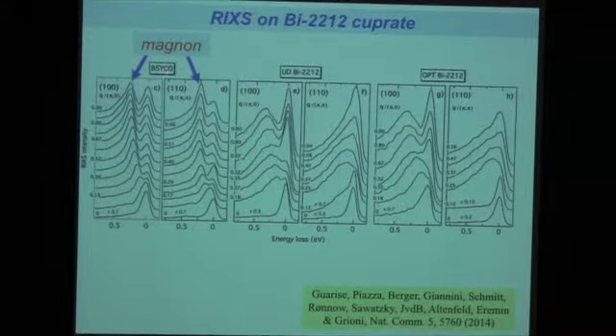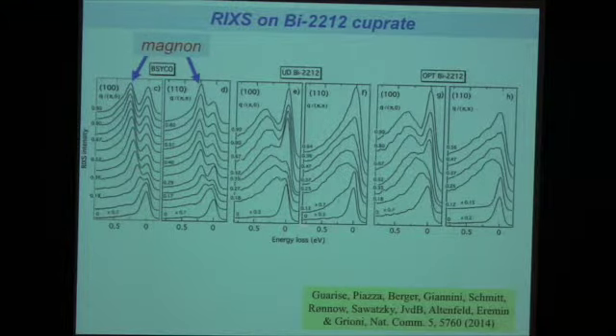Now, this is not doped, an undoped system. This is an under-doped system. This is optimally doped Bi-2212 superconductor. So these are now two directions. This is again momentum going to (π, 0), so from 0 to (π, 0), and here momentum going from 0 to (π, π). For the undoped system, I have my nicely dispersing magnon sitting here in both cases, as it should be.